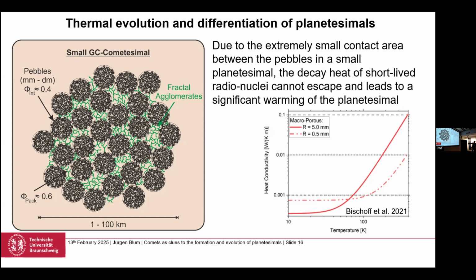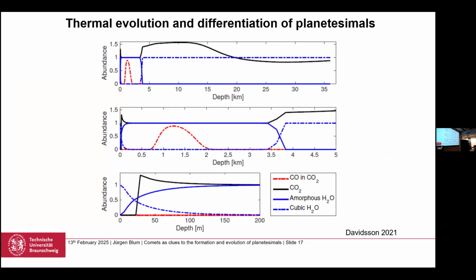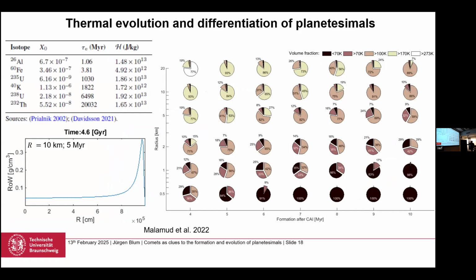And so then, of course, the radiogenic heat is generated and cannot be transported, so the temperature rises, but as the temperature rises, that drives the radiative heat conductivity up, and this is why the curves go up steeply. This is a temperature to the power of 3 effect. So in the end, at high temperatures, the conductivity is high. And we modeled the temperature evolution, Jürgen Blum modeled it, and he found differentiation, and we modeled it as well in Denver with Uri Malamud from Israel as first author.